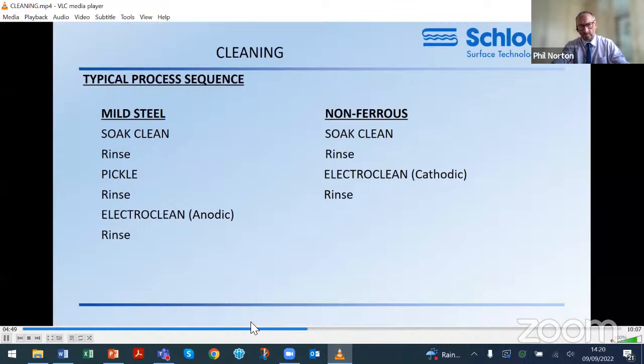A combination of cleaners is often utilised in sequence. For example, for mild steel, a strong caustic cleaner followed by a rinse, and a pickle followed by a rinse, and finally an electroclean and rinse. For non-ferrous, a mild alkaline cleaner or an acid cleaner to prevent surface attack, a rinse, and an electric cleaner followed by a final rinse.